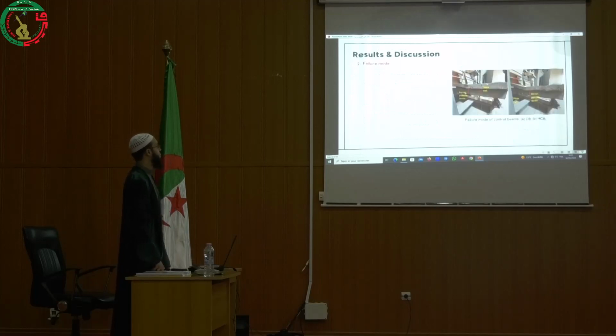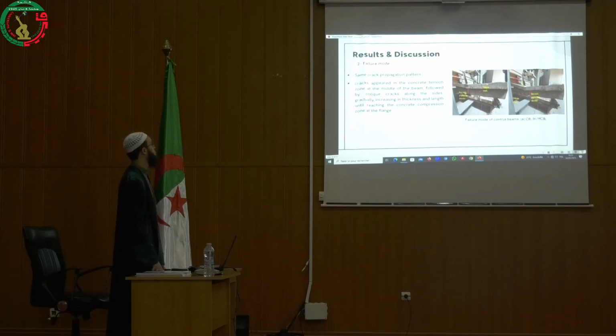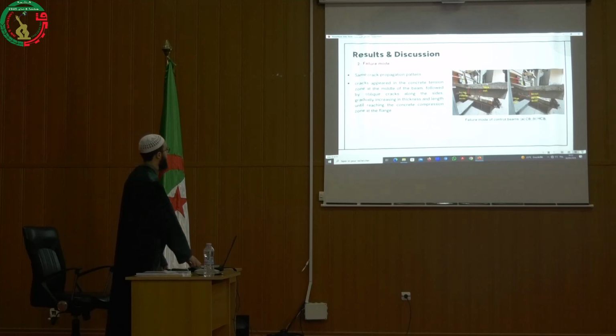The following pictures show the failure mode of control beams, the solid on the left and the hollow on the right. A similar crack propagation pattern was observed in both solid and hollow beams. The crack appeared in the concrete tension zone at the middle of the beam, followed by oblique cracks along the sides, gradually increasing in thickness and length until reaching the concrete compression zone at the flange, resulting in a flexural failure, as you can see.